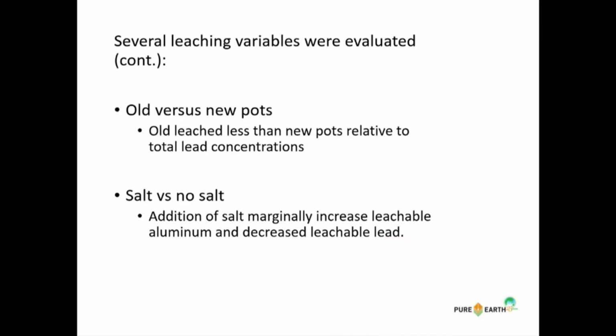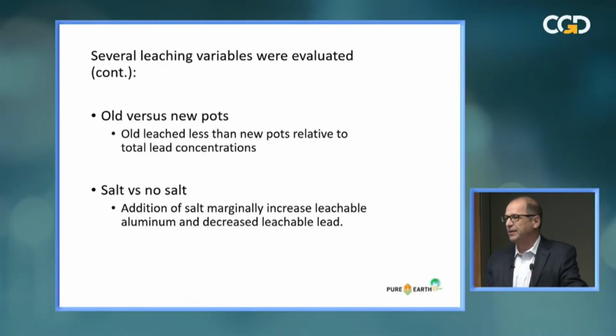We also found that old pots leach less lead proportionally than the new pots. We'll also get back to that. The addition of salt, common in cooking, we found that there was a marginal increase in leachable aluminum, but not an increase in leachable lead. It was a marginal decrease.